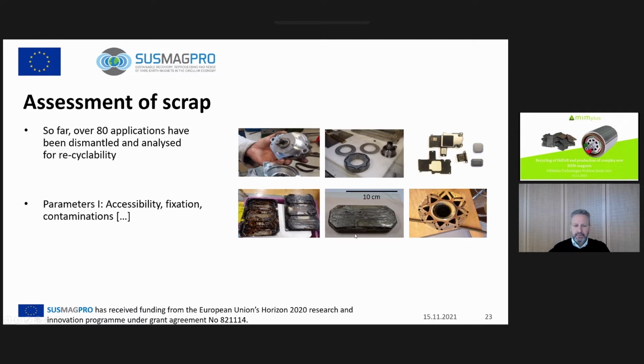If you look at fixations and contaminations, for example, wind turbines are a perfect source because there's a lot of magnets at one place. But in this case, the magnets are housed in a stainless steel casing and they're glued in with a glue which decomposes when you thermally demagnetize the magnet and leads to massive contamination. Or here you see the traction motors where the magnets which you see here are fairly difficult to access or to separate.